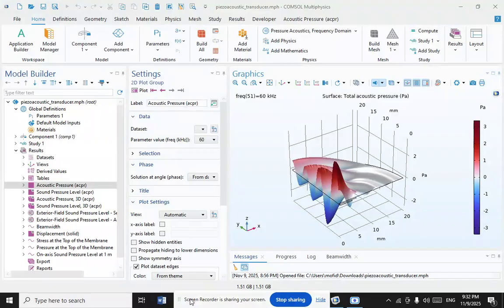In addition, while low cost lead zirconate titanate transducers were previously used as buzzers for sound generation, there are also studies where they are used as acoustic sensors for structural health monitoring. Moreover, PZT transducers and acoustic emission sensors are also used together to measure the surface quality in grinding processes, and it was determined that the AE sensor and PZT transducer give similar responses to the stimuli from the grinding process. In a similar study in which AE sensors and PZT transducers were compared by applying the PLB pencil lead break test on aluminum ceramic material, it was determined that the obtained frequency values showed that the PZT could be used as an alternative to AE sensors.